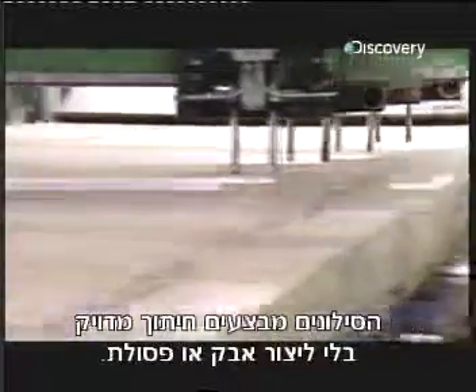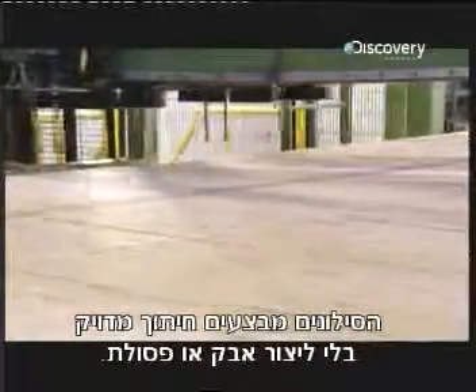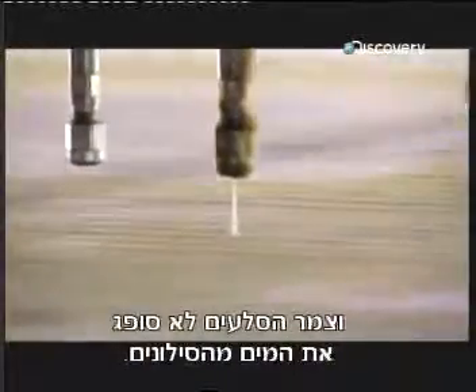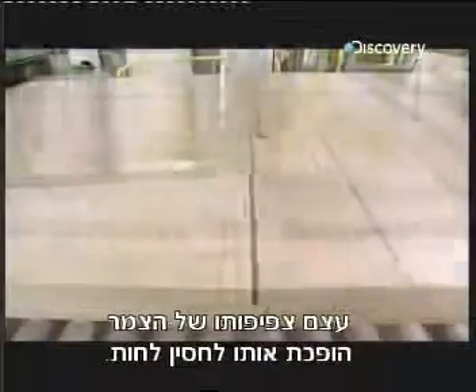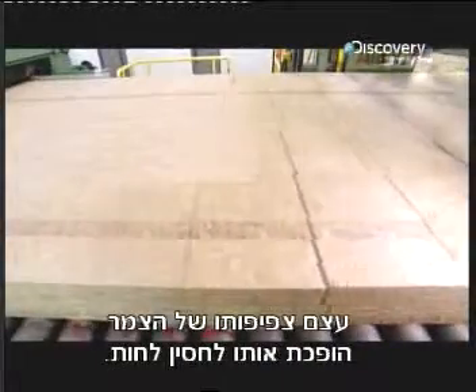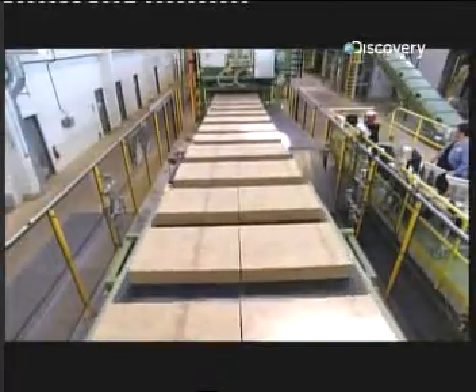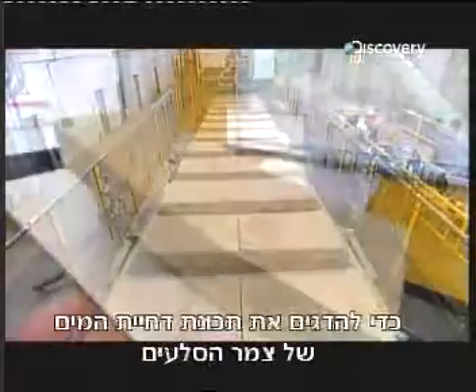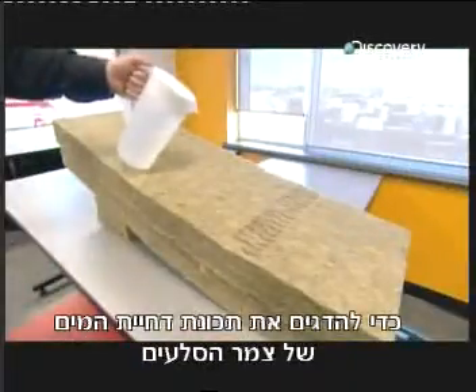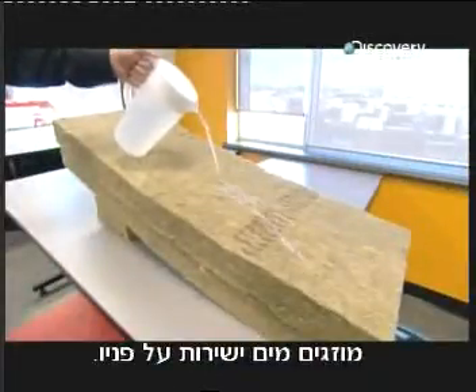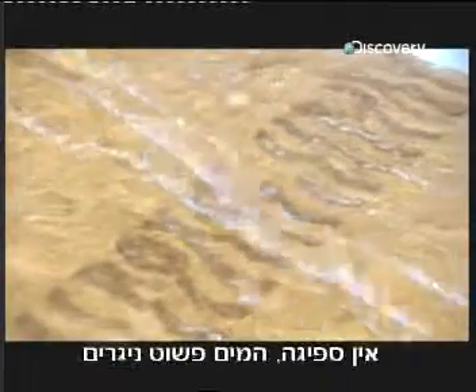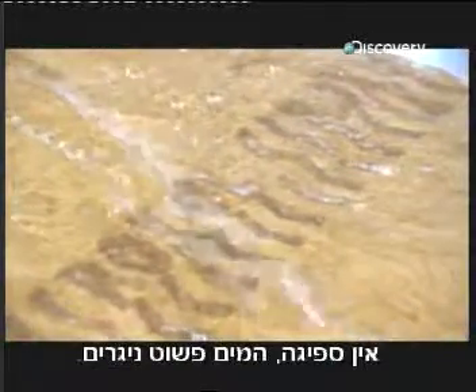The jets do a precise job without generating dust or waste. And the stone wool doesn't absorb the water from the jets. Along with the oil added to the fibers during the spinning, the sheer density of the wool makes it moisture-resistant. To demonstrate the stone wool's water-repellent qualities, they pour water directly onto the surface. There's no absorption. The water just runs off.